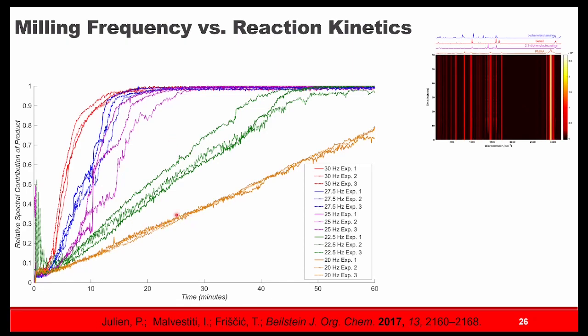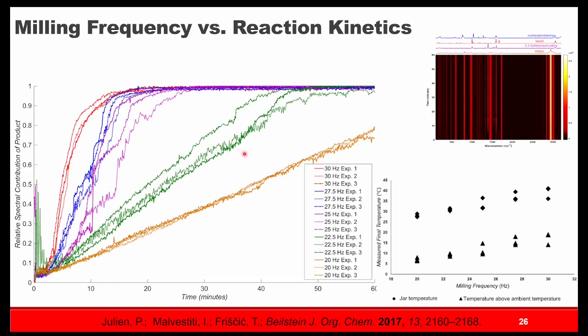What we see is we're starting off with linear kinetics, and then eventually we get something sigmoidal. It looks kind of exponential, but it really is sigmoidal. There's a lot of noise here at the beginning because you don't get as much sample in your beam path for Raman. So this is a bit of an artifact, but the rest of the curves are actually reasonably accurate.